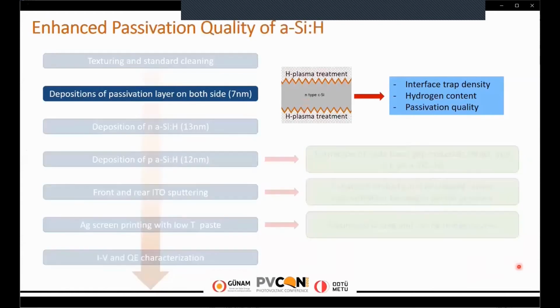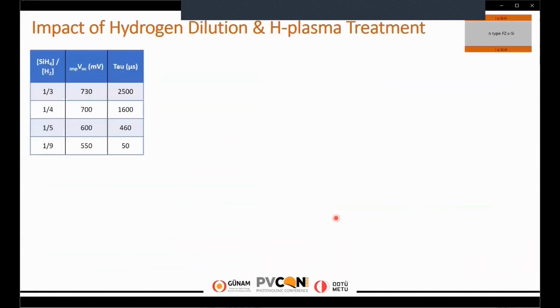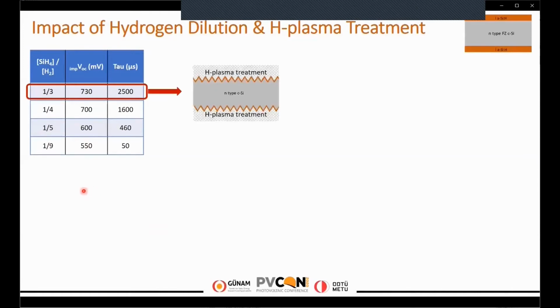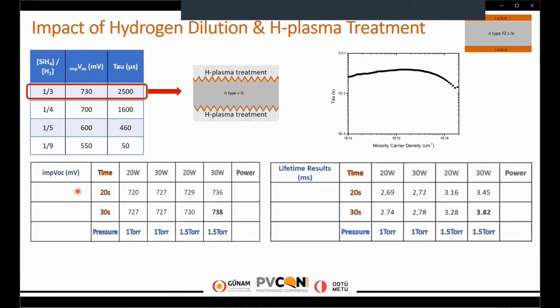Okay, let's move on. Enhanced passivation quality of the amorphous silicon layer. On the left-hand side, you can see the impact of hydrogen dilution ratio on the passivation quality of the amorphous silicon layer. When you increase the hydrogen dilution ratio, the implied VOC values decrease and effective lifetime values decrease. Up to now, we picked 1/3 hydrogen dilution as the optimum value. Then we inserted the hydrogen plasma treatment right after the deposition of the amorphous silicon layer. For the optimization of the hydrogen plasma treatment, we changed plasma duration, plasma power, and pressure. The results are given in the tables.